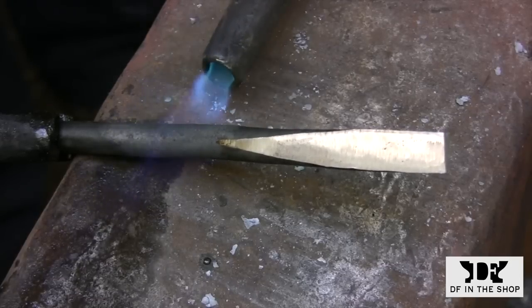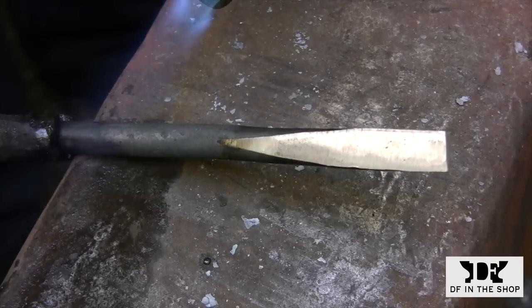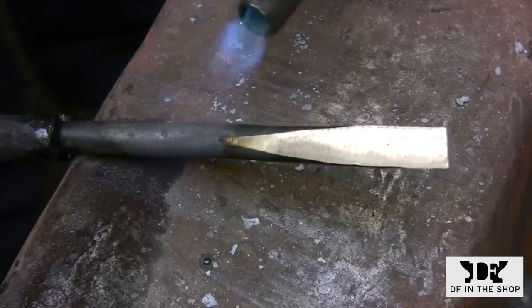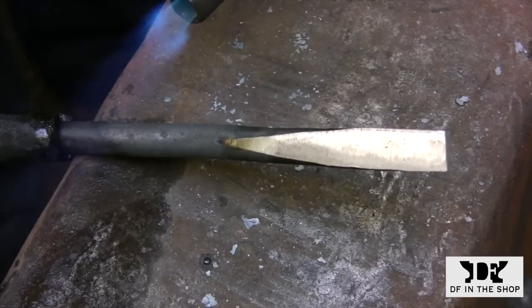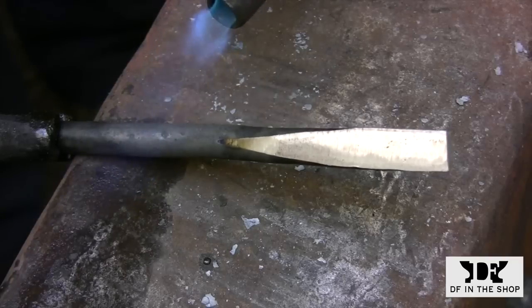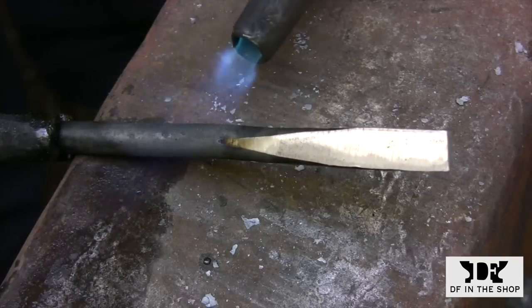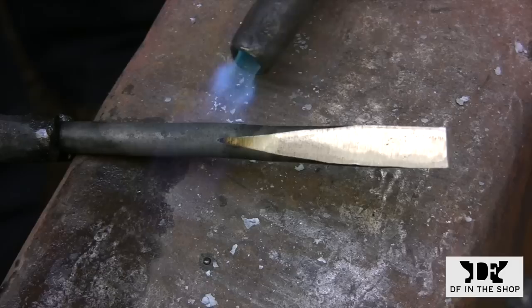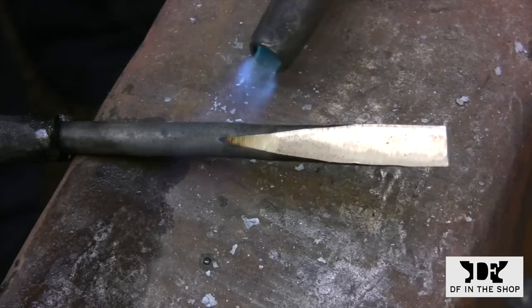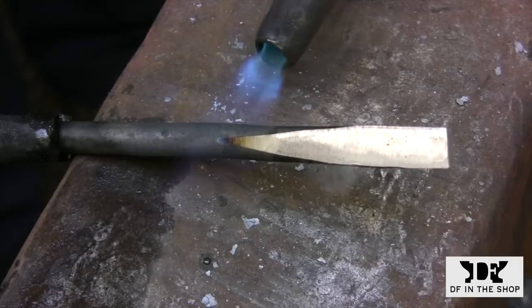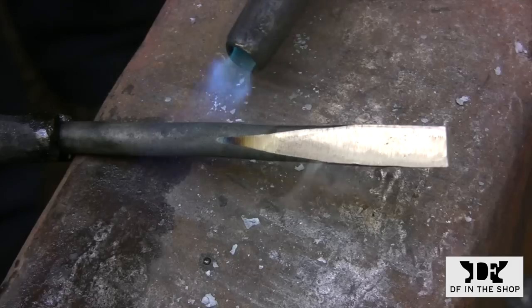Now this was a tool that was quenched in oil, and you can start seeing the oil starting to burn off right now, and that happens just before you start seeing the straw color. So at this point I'm going to ease up on the torch, and I'm just going to apply the heat when I see that the colors are starting to slow down a little bit.